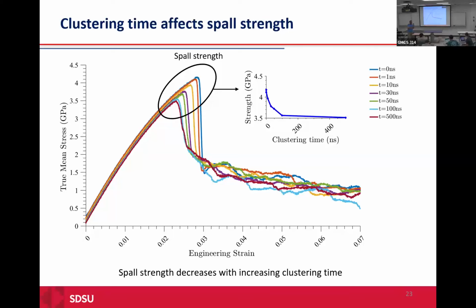Yeah, there's two things. I mean, this is a very complicated topic, right? So the first part is when you are propagating the shock wave, you have the compression phase of the shock wave, which is really propagating forward. So that's where you tend to create a very high hydrostatic state of stress, and the hydrostatic state of stress is what causes the voids to start to nucleate. Now, on the returning wave, it pulls that apart. And that's what causes the spall plane to start to nucleate. If you have a very high state of tensile stress returning, you actually can take the whole chunk of the material out. And the depth of that will tell you the strength of the material and all these things.